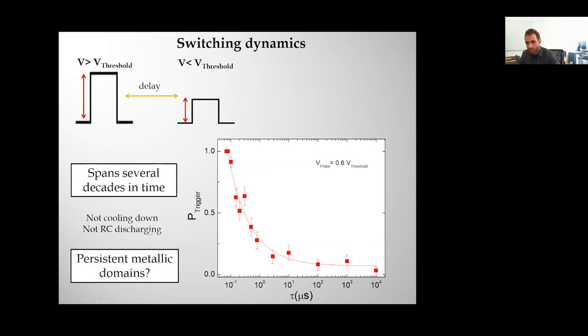So it cannot really be cooling down, or any RC charge time constant of our circuit, because that's in the nanosecond timescale. So what can it be? One of the things that we thought is that maybe for some reason we have some metallic domains that, while most of the device relaxes into the insulating state, are persistent. For some reason they are very long-lived and they stay in the device, and somehow they make it easier for you to trigger the transition again.